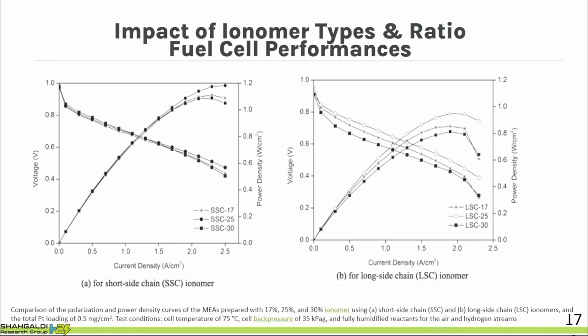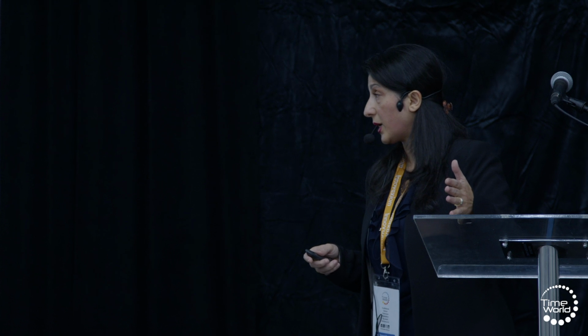In the other work that we did, we applied short side chain ionomer and long side chain ionomer with different ratios to understand, if we have a commercial catalyst, what ionomer is best for us and how we can figure it out under the same method of mixing. We understand that if you're using shorter side chain ionomer under high flow, we make sure that we don't have flooding, because when we have high flow of reactant, all the flooding problem will be solved by itself.